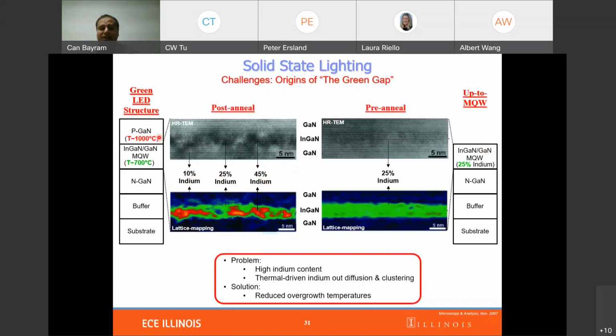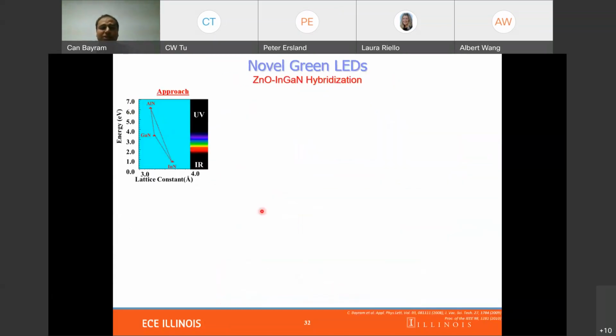The problem is basically the higher temperature of p-gallium nitride. This is because of the chemistry of the system as well as deposition techniques. You increase the temperature from the quantum well to the p-gallium nitride, and mainly your high indium content and the thermal diffusion of indium out of your quantum wells creates non-uniformity and performance problems. So the question came, can we reduce these growth temperatures?